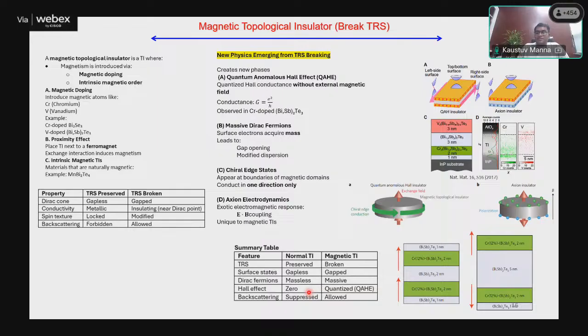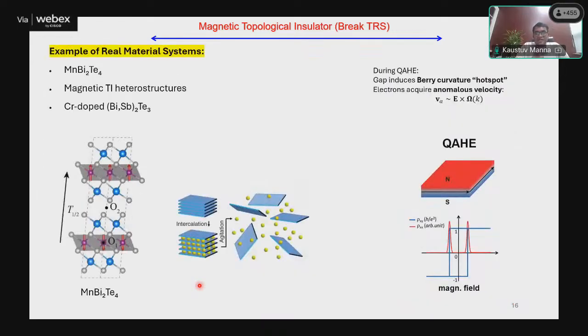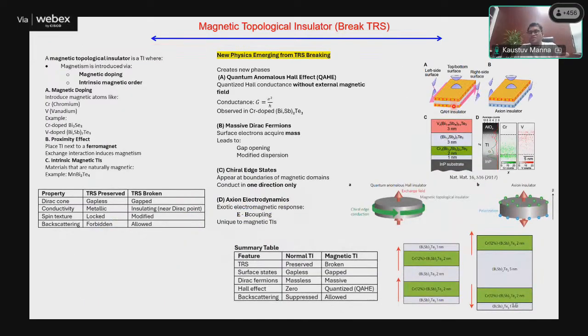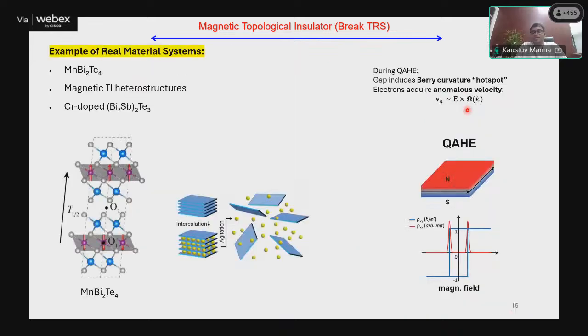It depends on the situation. The Hall effect in this case is zero, whereas in this case you can get the quantum anomalous Hall effect. So like that, these are different states. Here I am showing the manganese bismuth telluride. I said that this is one of the rarest examples. For example, if you want to have a proximity effect, you need to use MBE and do the deposition. But in MnBi2Te4, this is the bulk compound, you can get the same effect. See, manganese bismuth telluride, you can observe it as a layer.